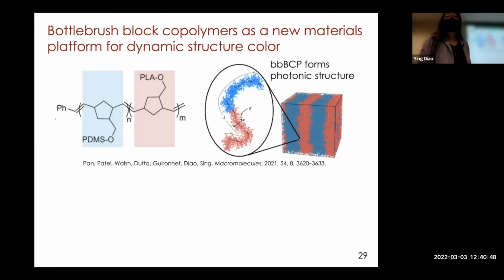Okay, so here are the polymers that can potentially enable dynamic structured color. It's called bottlebrush block copolymers. It has a polynorbornene backbone, and there are two distinct chemical blocks. One is based on PDMS, the other is PLA. They have different chemistries that I didn't show here. So this polymer literally looks like a bottle brush because there are these hairs densely grafted on the backbone.